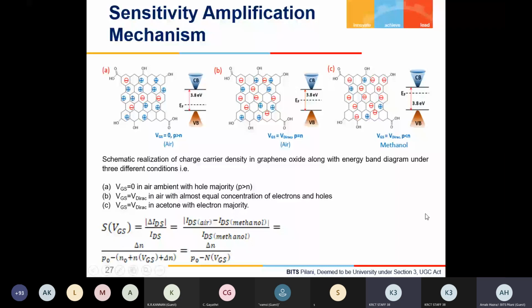Here you can see the energy band diagram of graphene oxide. This is slightly different compared to the pure graphene I have shown, because graphene oxide has an optical band gap. This band gap is quite high, 3.8 electron volts. So the conduction band and valence band have been shifted, showing this band gap. This is the graphene oxide layer, with different functional groups. Now we are considering air ambient when the gate to source voltage is 0. Of course, the Fermi level will be closer to the valence band, so you can see the hole concentration is much more. That is the blue positive sign as compared to the negative sign.